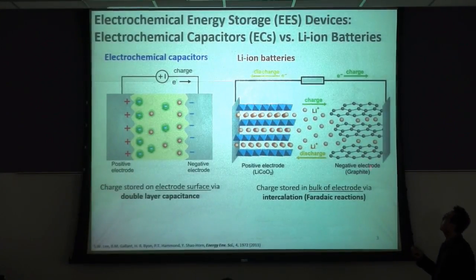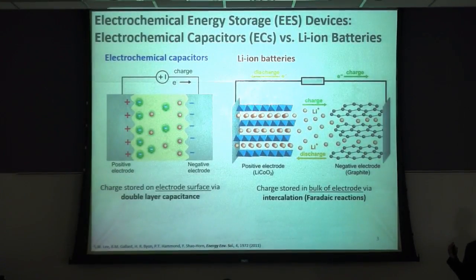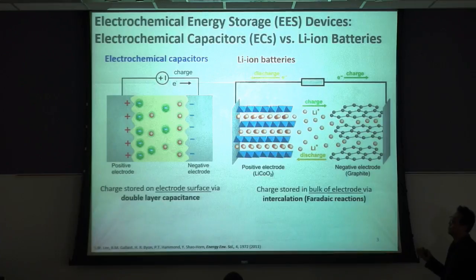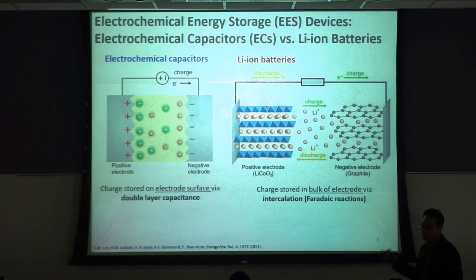On the other hand, lithium-ion batteries store charge in the bulk of electrode materials. These are examples of the conventional lithium-ion batteries, consisting of a lithium cobalt oxide positive electrode and a graphite negative electrode. As you can see, both electrodes have layered structure materials. So during the charging and discharging process, lithium ions intercalate and de-intercalate. Basically, we fully utilize the bulk of the electrode material for charge storage.